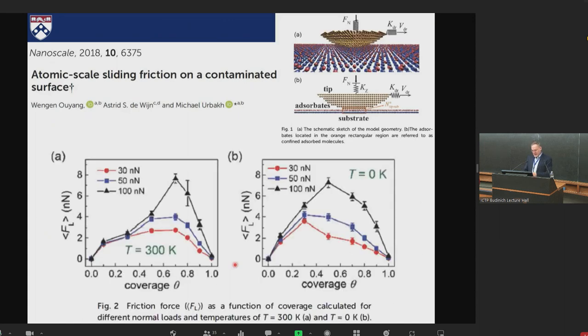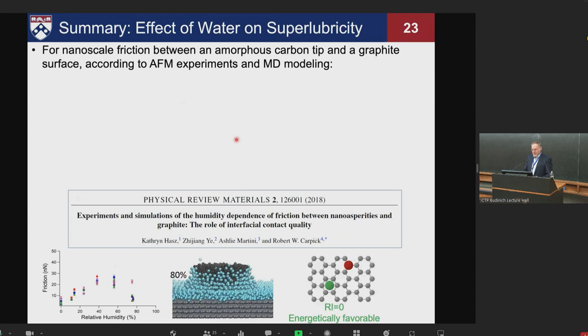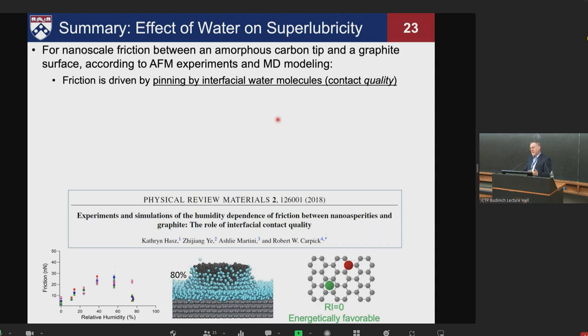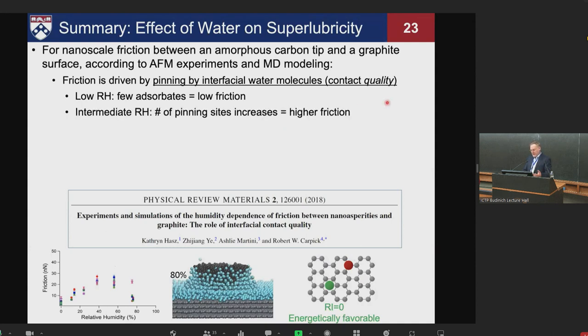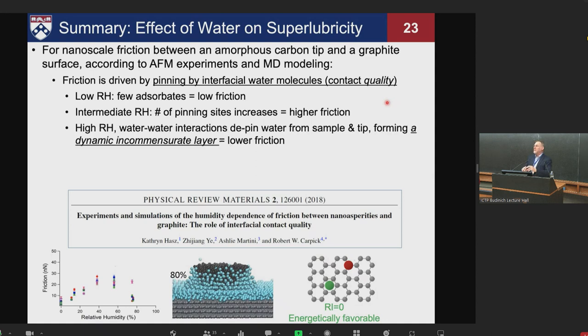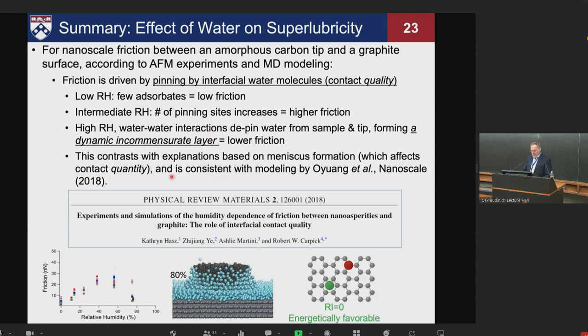So I'm going to skip this, but I will say Michael Urbach and Astrid de Wijn have a general model that saw something very similar, friction versus coverage of generic adsorbates, that is consistent with this idea. So we see that with this amorphous tip and a graphite surface, the pinning of water molecules, in other words, this contact quality, leads to higher friction. Low friction with few adsorbates, pinning sites at intermediate humidities, but at high humidities, the layer depins because of the lateral interactions as the water forms an ordered layer. Okay, and this contrasts with that meniscus idea, that capillary idea I mentioned, but is consistent with the work of Michael and Astrid. I think it's probably time to wrap up.